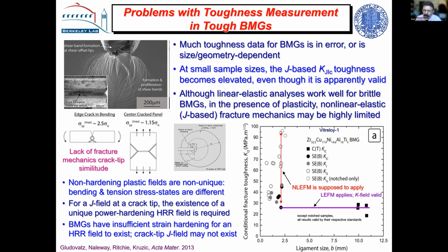And I think we don't know precisely, but we think the reason is that when you're using linear elastic fracture mechanics, everything's fine. But when you go into the non-linear elastic fracture mechanics regime, remember, you have to have a Hutchinson-Rice-Rosengren field that's unique at the crack tip. And that field is a field dominated by strain hardening. It's that local degree of strain hardening that gives you the uniqueness that you can measure the toughness in that non-linear elastic regime. If you go to full plasticity in any material, then the fields just are not unique anymore. The bend fields and tension fields are totally different. But you can get away with it in the non-linear elastic fracture mechanics because of that zone of hardening.